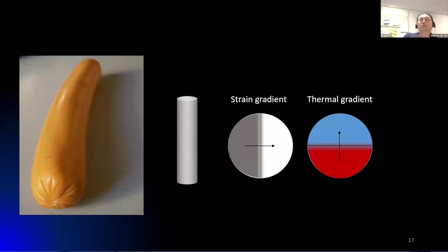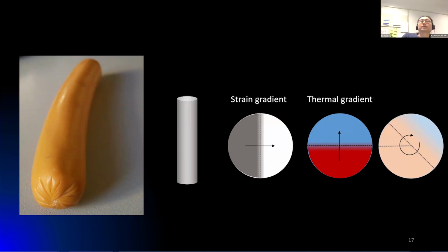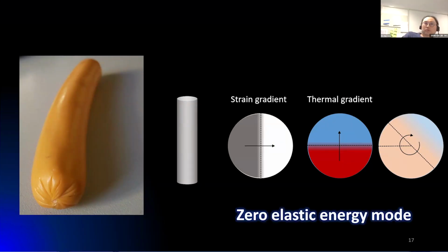If you cook the sausage, it may shrink. It depends on what temperature you have. But there's a thermal gradient, and the thermal gradient will induce a strain gradient. These two strain gradients do not match each other exactly. They are in perpendicular directions, and it generates a torque that makes the system roll on the hot plate. And this is called the zero elastic energy mode. You don't need to control the structure, you just put it on the hot plate. Because of these two gradients, it automatically rotates.